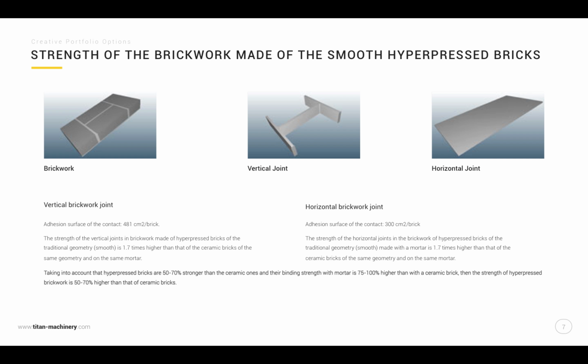Horizontal brickwork joint. Adhesion surface of the contact is 300 square centimeters per one brick. The strength of the horizontal joints in the brickwork of hyperpressed bricks of the traditional geometry, smooth, with a mortar is 1.7 times higher than that of the ceramic bricks of the same geometry and on the same mortar. Taking into account that hyperpressed bricks are 50–70% stronger than the ceramic ones and their binding strength with the mortar is 75–100% higher than with the ceramic brick, then the strength of hyperpressed brickwork is 50–70% higher than that of ceramic bricks.